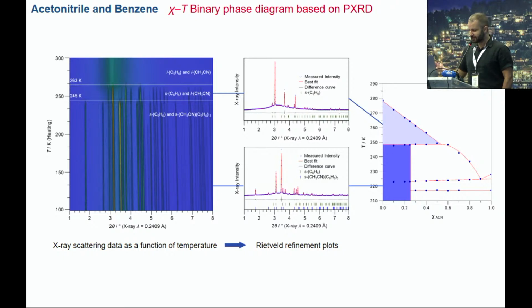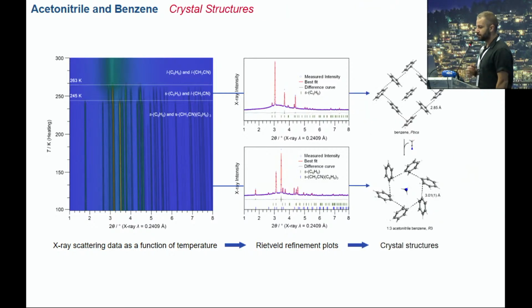But it's important, and it's fun, and we did it. And in this case, we can see very interesting chemistry. We see that up there, we have a solid benzene and liquid acetonitrile. And acetonitrile, below the peritectic line, penetrates the crystal structure of benzene and adopts a channel structure in which we have acetonitrile within the channels of benzene. This is a very, very typical peritectic phase transition. Now, this co-crystal would be stable on Titan.